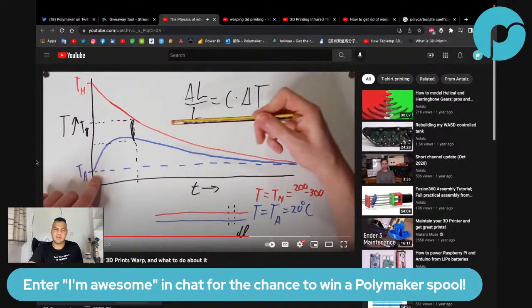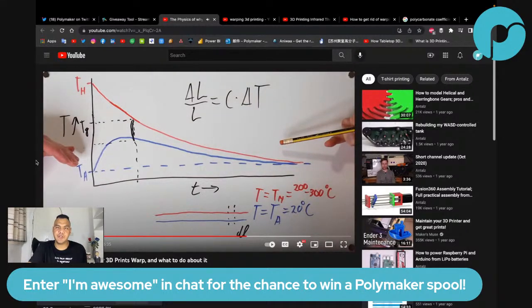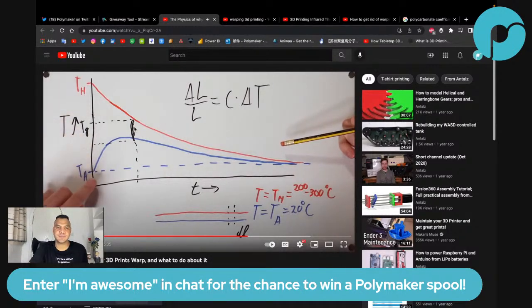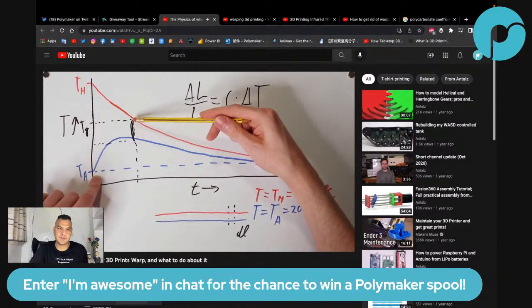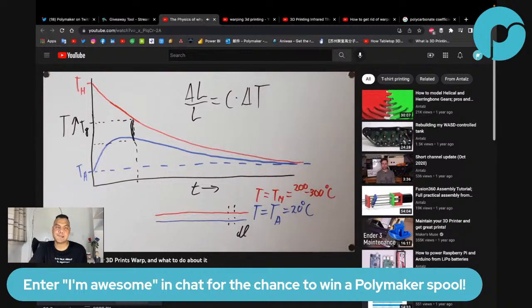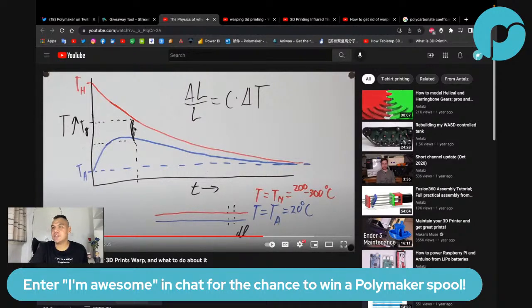Let's listen to that again. Has less of a gap to close, increase it. So you increase the ambient temperature, and if you increase the ambient temperature, then that means, let me think. Okay, yeah, it should close the gap, I guess. Because that means that the lower layer has less of a gap to close, and then this difference becomes smaller automatically. And you also start losing a lot less heat to the atmosphere because it's warmer. And the way, of course, you do this is by putting your printer inside of an enclosure. We can now also better understand why some materials move the TG curve up. Yeah, I got it.